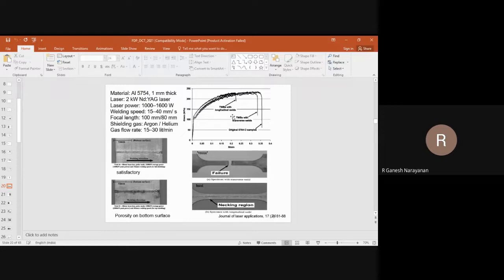Okay, and you can see the transverse weld fails in the weld zone, I told you. And the longitudinal weld, in the bottom photo, you can see it fails perpendicular to the weld. And you can see typical stress-strain behavior. You will see the longitudinal weld has got lower ductility as compared to transverse.